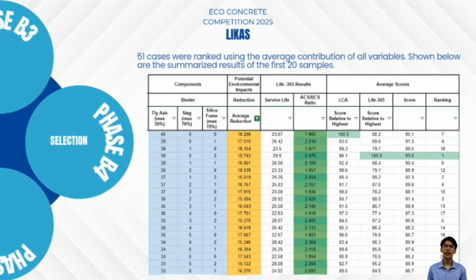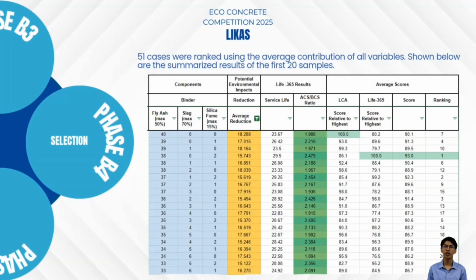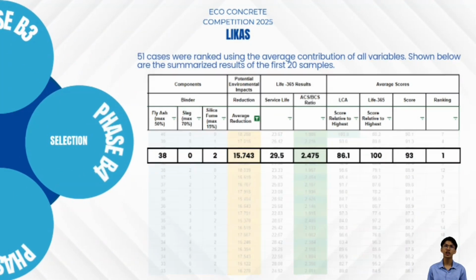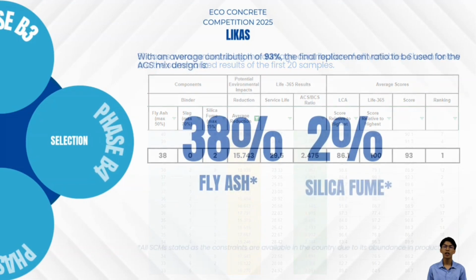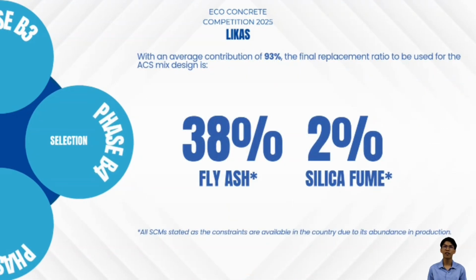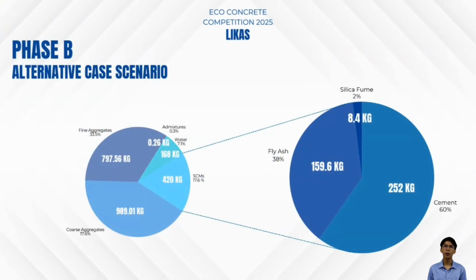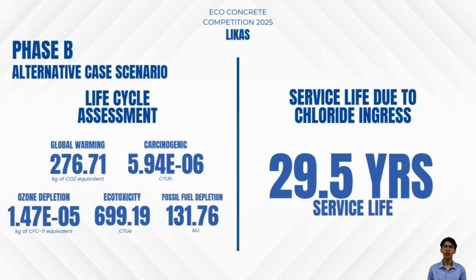For phase 4, we select the final replacements of all SCMs based on their contribution. Out of all samples, a ratio of 38%, 0%, and 2% of fly ash, slag, and silica fume was recorded to have the highest contribution of 93%. Thus, the final cement replacement consists of 38% fly ash and 2% silica fume. Shown is the final components of the ACS mix proportion with a breakdown of cement replacement as shown on the right side. To break down the results of ACS in terms of LCA, the ACS has recorded as shown.